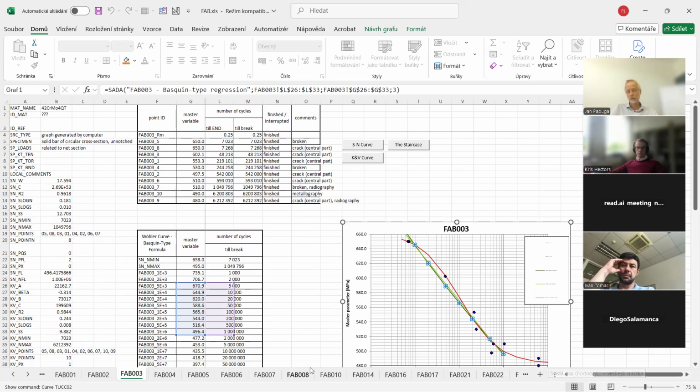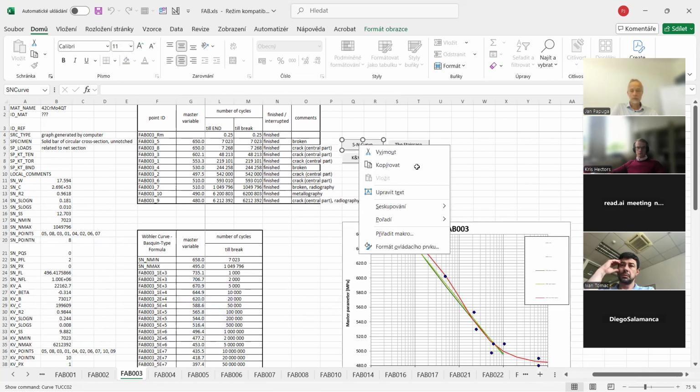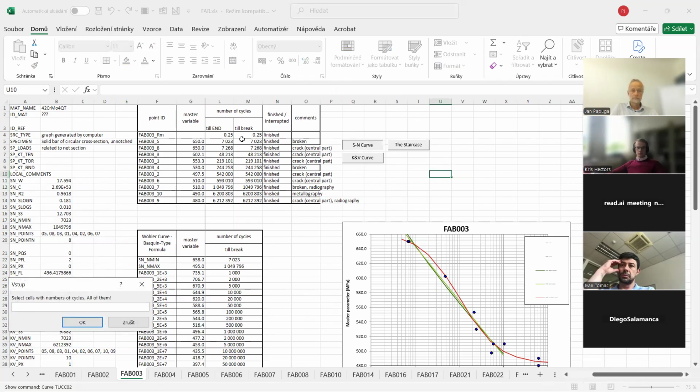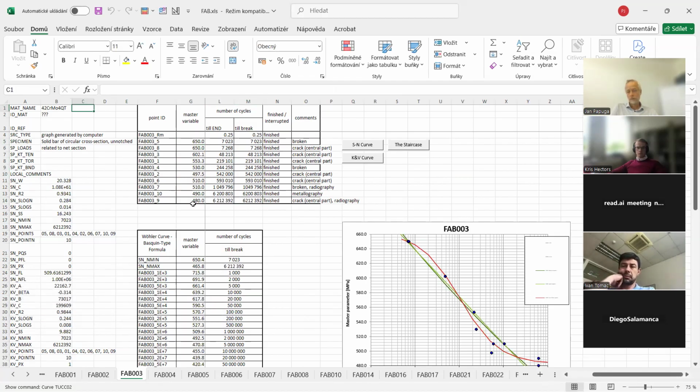But if I also include these data points, because they are there, I get a curve which theoretically fits all data, but you see that the standard deviation of logarithms got, say, 50% higher. And it is also visible that very likely the change of the trend is here.